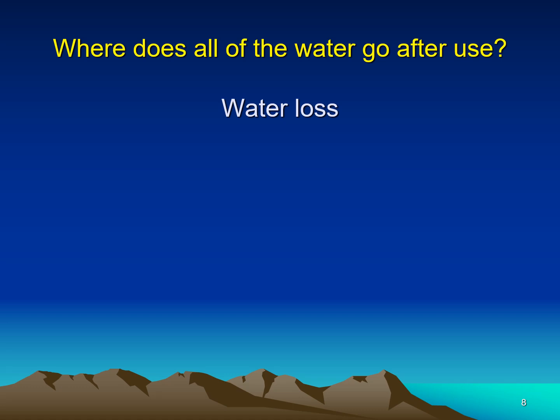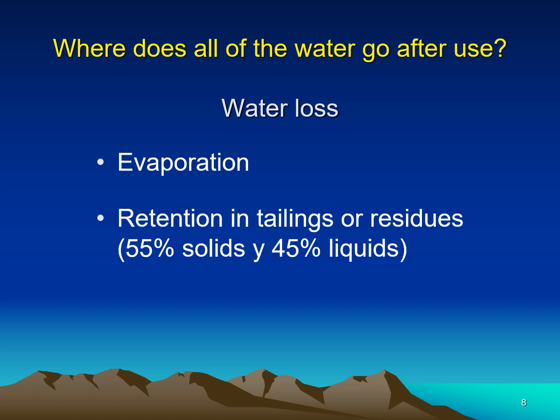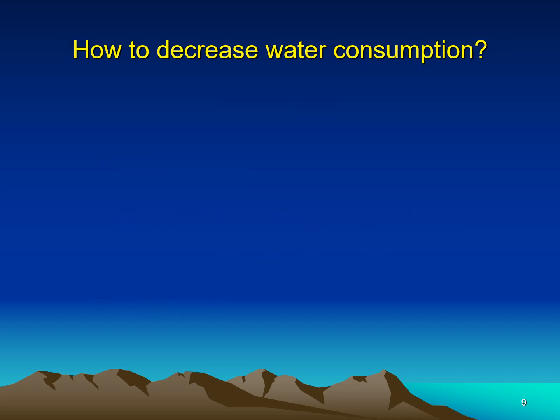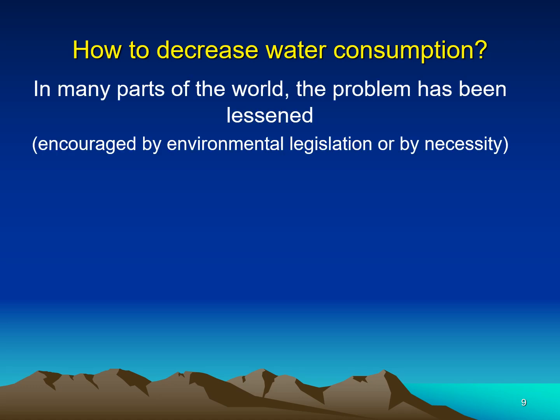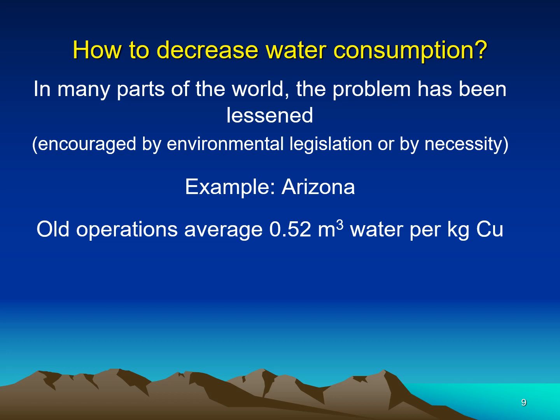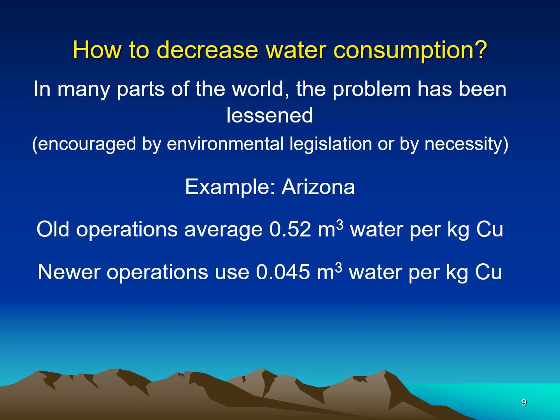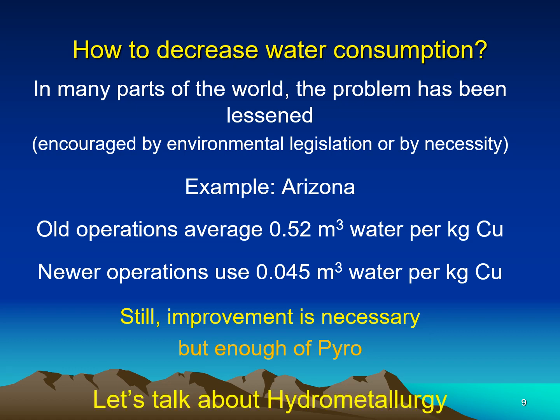Where does all the water go after use? Well, we have quite a bit of water loss by evaporation, retention in tailings or residues, about 55% solids and 45% liquids, and infiltration. How can we decrease water consumption? In many parts of the world, the problem has been lessened, encouraged by environmental legislation or by necessity. For example, in Arizona, in the older operations, there's an average of half a cubic meter of water per kilogram of copper. In the newer operations, there's less than 10% of the water used per kilogram of copper recovered. Still, improvement is necessary. But enough of pyrometallurgy. Let's talk about hydrometallurgy.